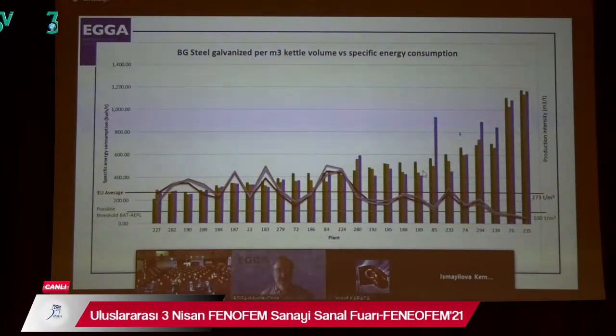And the answer to that question is no, because we've plotted on this chart the other line, the continuous line, which is the tonnes of steel processed per cubic metre of their galvanising bath. Because if you have a bath of molten zinc, it consumes energy even if it does nothing. If you have no production, you have still an energy use. So the level of production, the level of throughput of the plant is the main determinant of the energy efficiency.